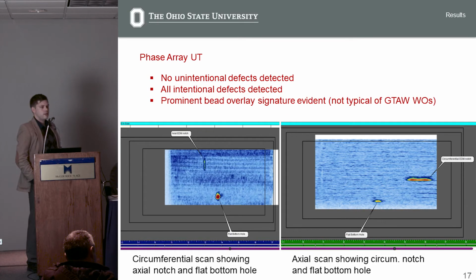The results of the phased array UT test were pretty good. No unintentional defects were detected, and all intentional defects were detected. In addition to that, a prominent bead overlay signature was evident, which is not typical in GTAW weld overlays and therefore not expected. So one concern in the report was raised that if a weld operator was running this coupon without prior knowledge of its fabrication, they might accidentally give a false positive to defects based on this grain structure that the technique revealed.